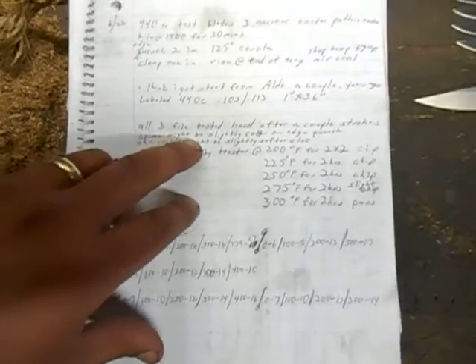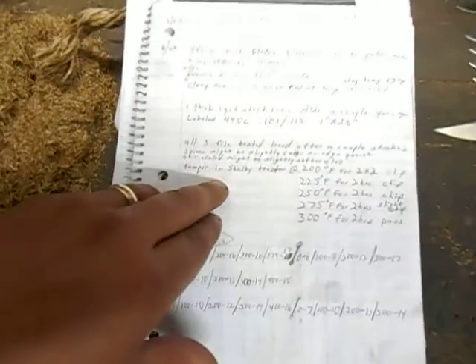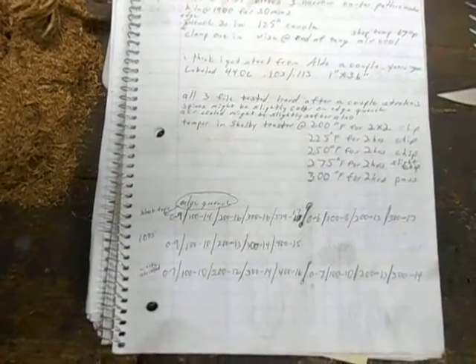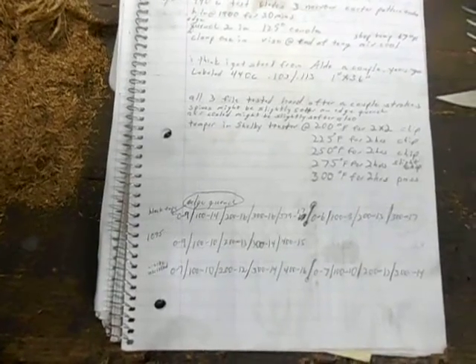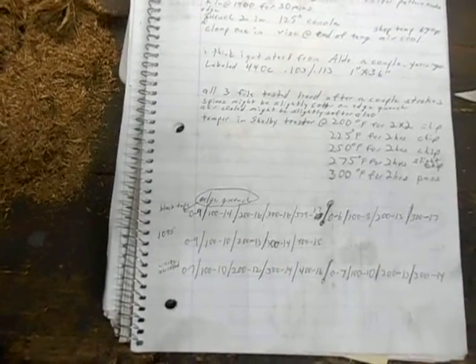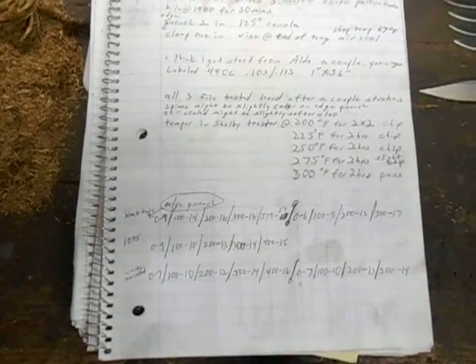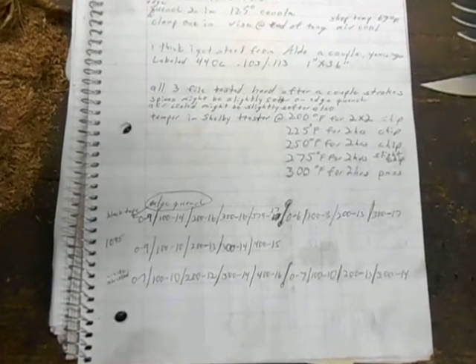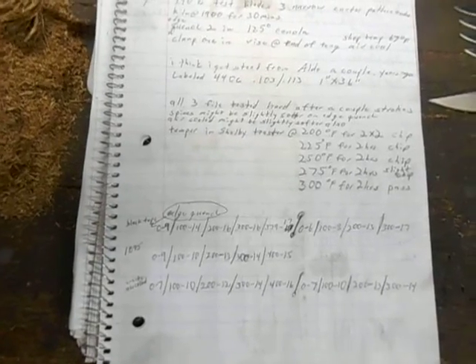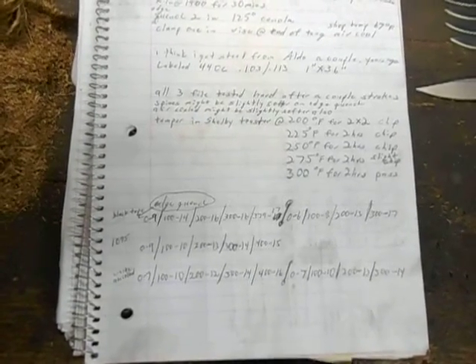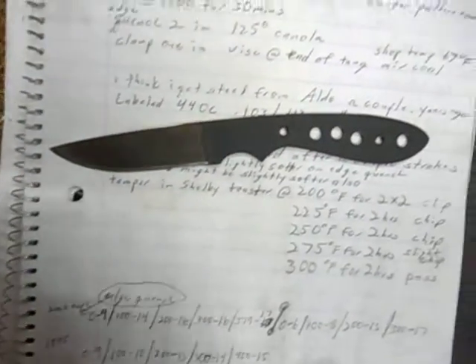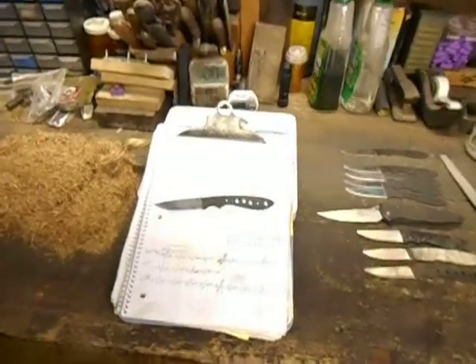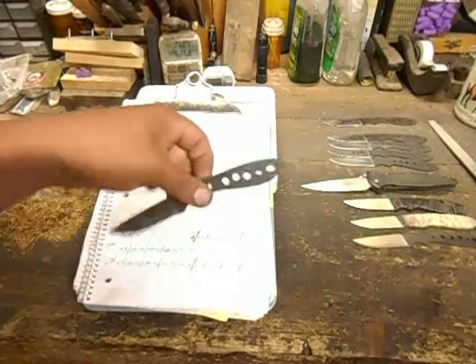All 3 of them tested hard with the file after a couple of strokes. Now here's another thing. I did not wrap these in foil. First of all, I don't have any foil, and second of all, I do kitchen knives and EDCs. I do all my grinding after heat treat on a water-cooled belt grinder. So I wanted to see what the big scaling issue was that everybody talks about, why you have to use foil. Basically, this is it. Let me put the camera down and see if I can show that a little bit better. The scaling was really minimal.